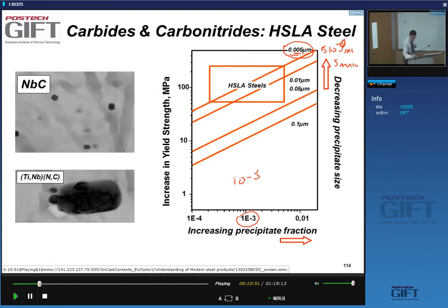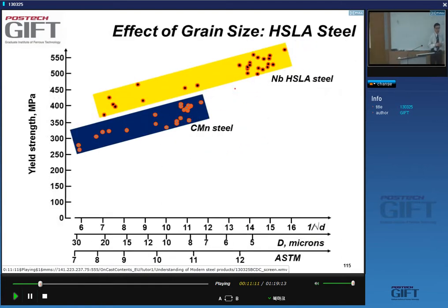And so if you have this concentration of particles, 5 nanometer particles, the strengthening they can give you is about 100 megapascal, yes? And so the strengthening effect in these HSLA steels is not only through precipitation. Actually, in general, the precipitation hardening is usually less than this 100 megapascal. You have an additional effect which results from the impact these precipitates have on the recrystallization, and that's the